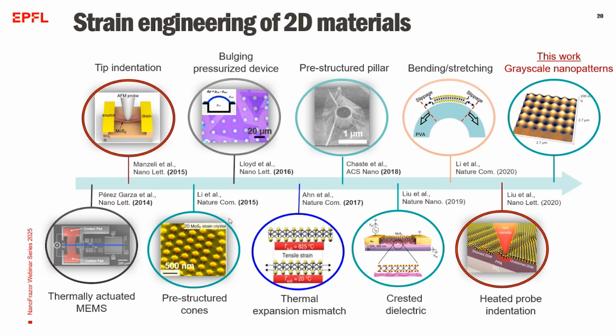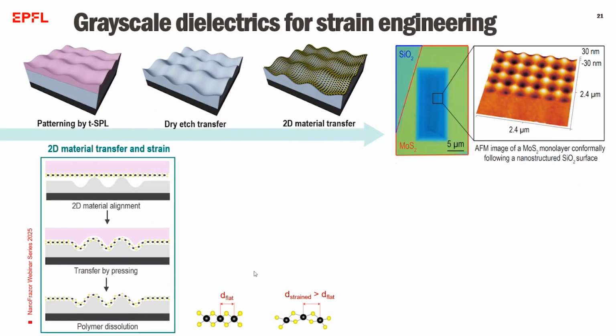And in our research also, similar to other pre-patterned techniques, we focus on pre-structured substrates, but with smooth grayscale surfaces to engineer mobilities in 2D material placed on top of them. And how do we do it? We use these pre-structured grayscale nanosurfaces as a platform to induce tensile strain in these atomically thin materials transferred onto them.